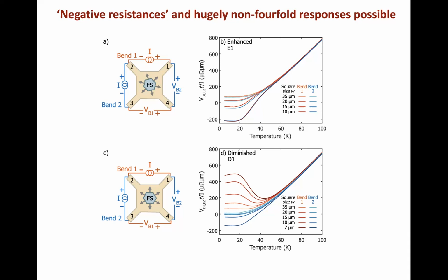Yeah, and at sufficiently low temperatures, you don't need to worry about electron-phonon umklapp. The way you tell that you've got phonon drag is that your measured resistivity looks activated, because you don't see resistivity from phonons until you bridge the umklapp gap. I see. So we knew from our resistivity that the standard Gurzhi resistivity of a single crystal was not seeing any of the normal electron-phonon processes. So all of those were going to be the friend of hydrodynamics, but we didn't know how many they were, right? And now we do know, and it doesn't match.